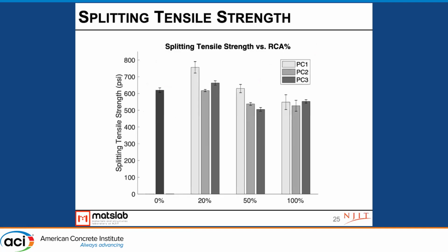This is the splitting tensile strength results. So if you just look at the very left, that's just the control group. What was interesting here is that the weaker parent concrete RCA groups actually had a higher splitting tensile strength, even at increasing percentages, than the rest of the groups. We weren't really focusing on this parameter, but it is interesting to note that the weaker parent concrete resulted in a recycled aggregate concrete system that actually had a higher splitting tensile strength.